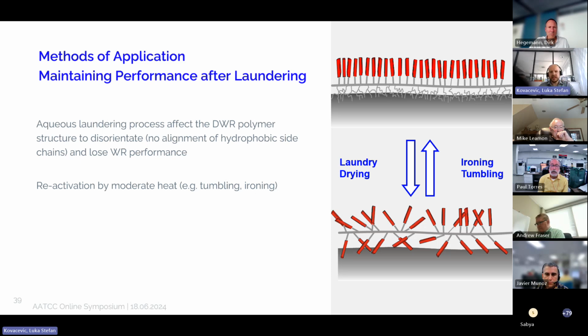Well, the thing is that after the finishing on the fabric surface, you have the polymers in an ideal crystallized way. You see those side chain modifications of the polymer. They are pointing away from the fabric, making a nice structure. After the laundering process, this polymer gets disorientated, loses not only structure, but also the repellent function. And this is why you have to apply heat by tumbling, by ironing, and by that you can melt these polymers, make them a bit more mobile, and these side modifications can realign, crystallize, and develop the initial performance again.